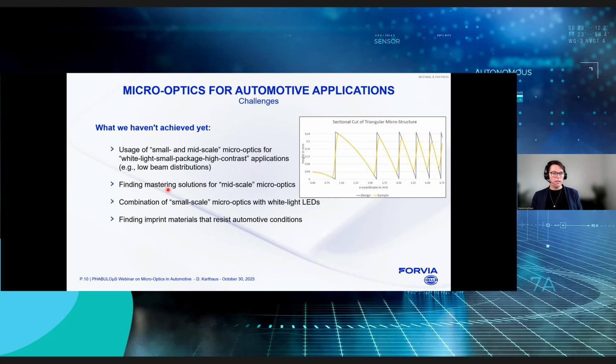And the reason, on the one hand, is that we need to find a mastering solution for these mid-scale optics. You see it here in the image. You see here a design in gray and a sample structure in yellow. And you see on the one hand that we get roundings at the edges, and on the other hand, the modulation depth of the structure is reduced when the periodicity of the structure is getting smaller, or say it in other words, when the slope angle is increasing. And especially for the structures that we evaluated, we have not found a mastering solution yet.